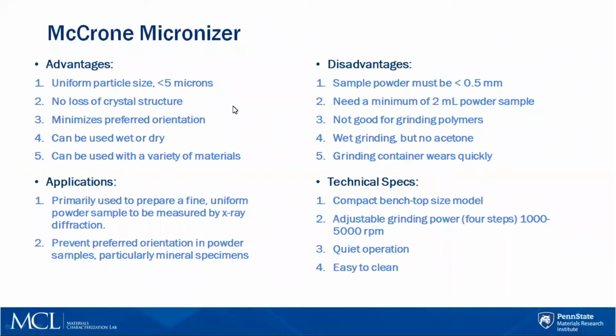The advantages of the micronizer are that it can reduce the particle size to usually less than 5 microns. You do not lose any crystal structure. It minimizes preferred orientation. It can be used wet or dry, and it can be used with a variety of materials.